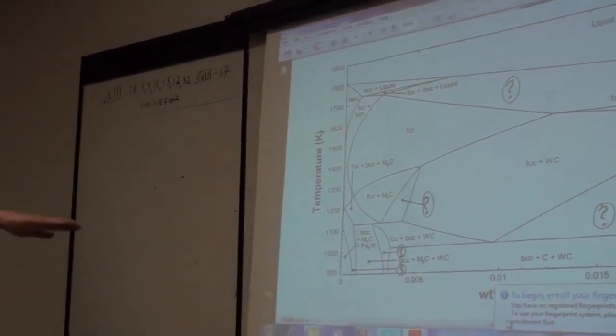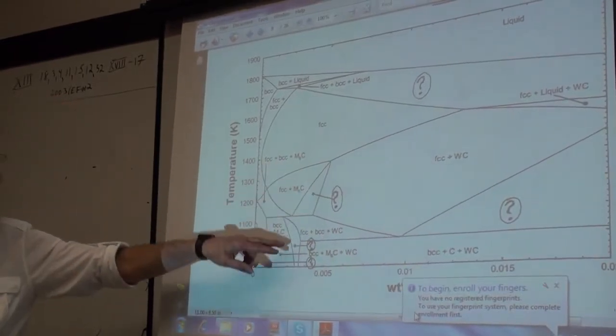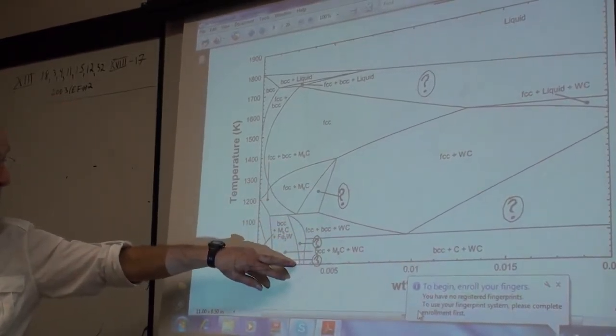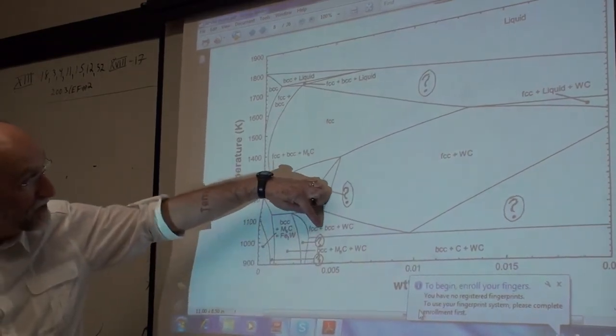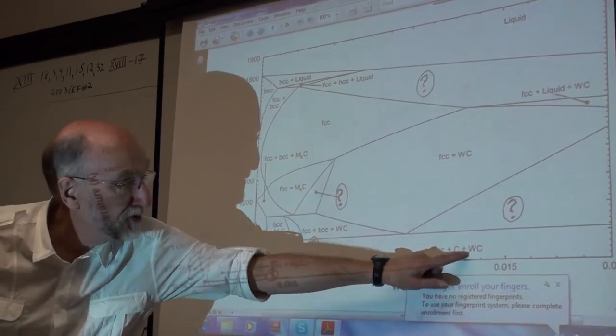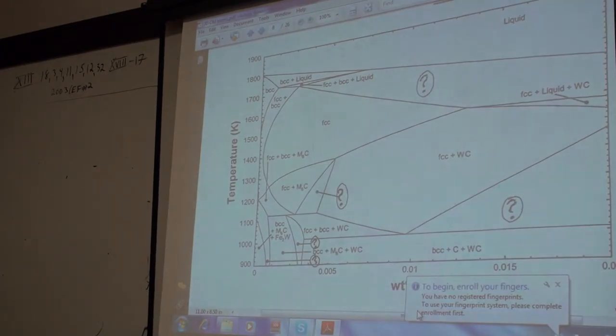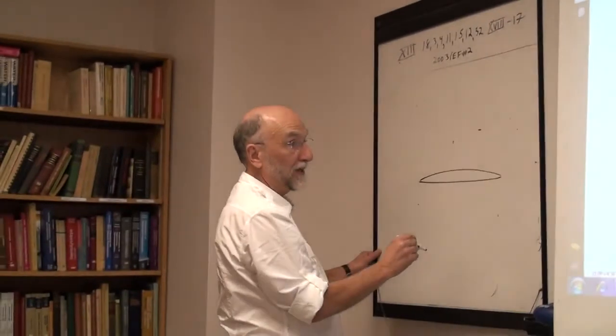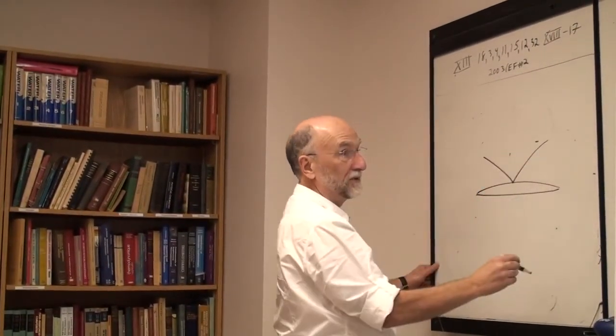And we have to consider this node here, and you have to be careful because that is a horizontal line. So this line here is not a phase boundary. It's a very narrow 4-phase region. As you can see, this region up here is FCC, BCC, WC. That's this region. You go down to this region, 2 things have changed. Okay, you've lost the FCC and you've gained the carbon. So this horizontal line over here is actually a very narrow 4-phase region that looks like that. These are your nodes.